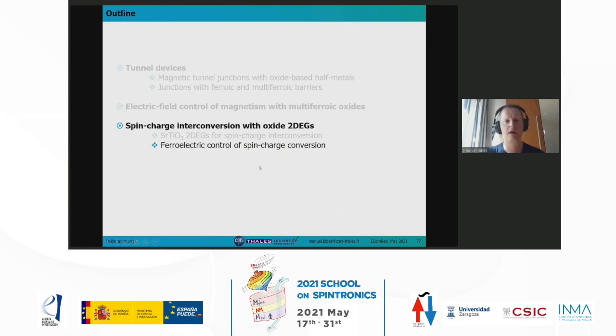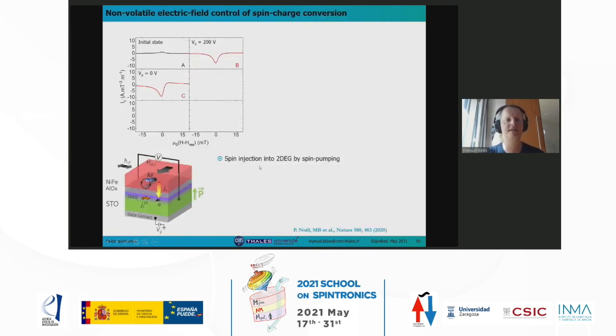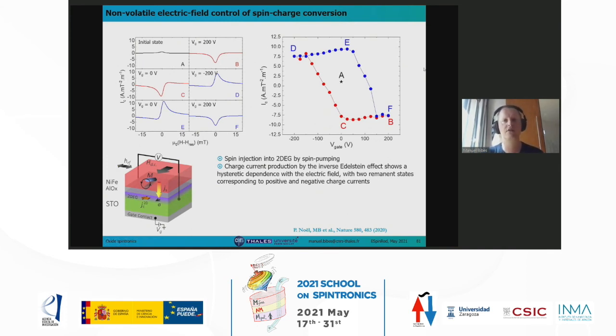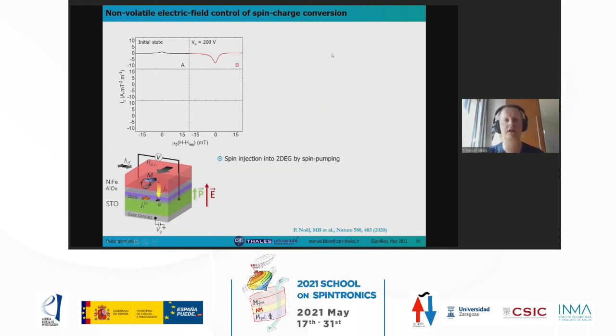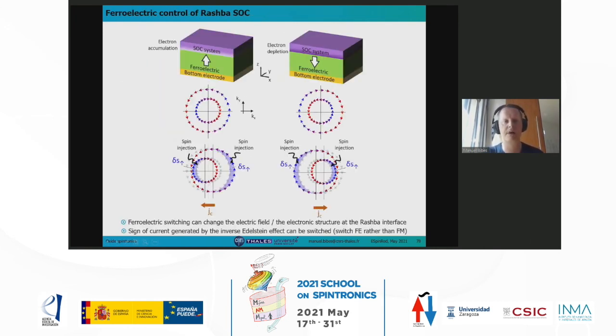Okay, so in fact, we did see the switching of the conversion due to, we think, the switching of the ferroelectric polarization, but we are not completely sure that this is the mechanism that I described here. This mechanism, as far as I know, has not been demonstrated yet, and I think maybe you are alluding to materials which are intrinsically ferroelectric and have Rashba spin orbit coupling, and there's a few oxides that have been predicted to show this. But another interesting system, which is not an oxide, is germanium telluride, which is a ferroelectric semiconductor, which has a switchable Rashba spin orbit coupling.